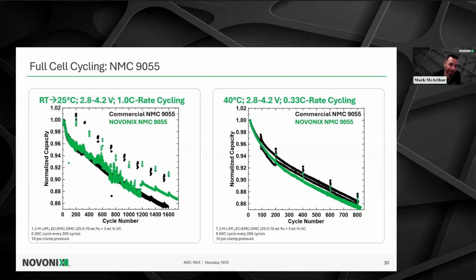So I want to illustrate the importance of temperature control on your battery cells whenever you're testing. The left-hand side is showing room temperature cycling to around 1200 cycles, and then the cells were removed and put into a very well-controlled temperature chamber at 25 degrees Celsius. And that's why the data for the NOVONIX material is so noisy up to cycle 1200, and it immediately flattens out as soon as you put it into a temperature controlled chamber.